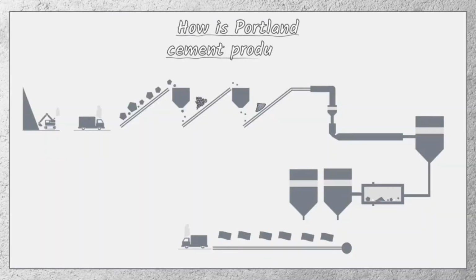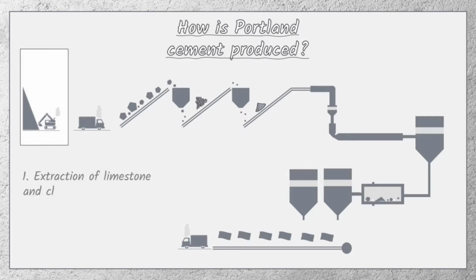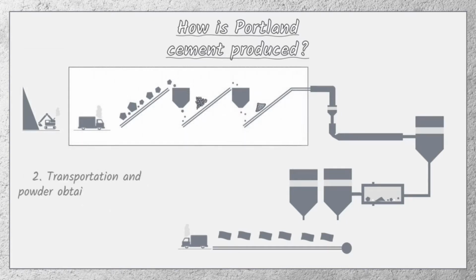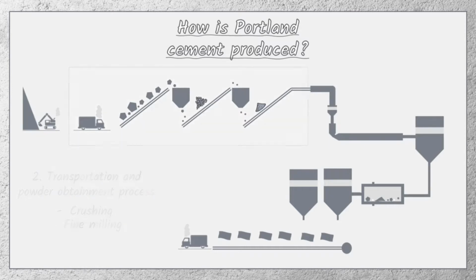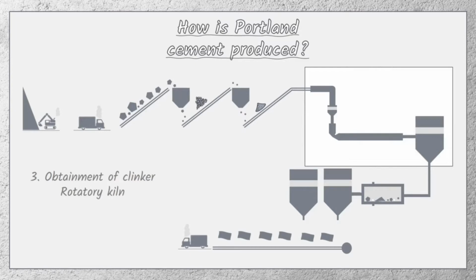The production process of Portland cement can be divided in 5 different stages. The first step is the extraction of limestone and clay from natural reserves, which will provide the main constituents of clinker. This extraction process produces large rocks which must be converted into fine powder. The rocks are transported and fed into a two-step milling process, initially with crushing of larger rocks and secondly with secondary milling. The fine rocks of limestone and clay are burned in rotatory kilns to form the reactive phases of clinker, which is the main phase of Portland cement and is responsible for promoting the hardening effect of this compound.